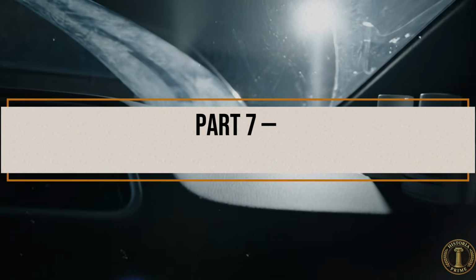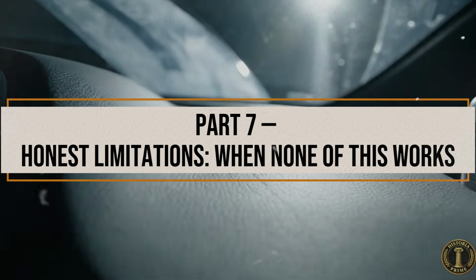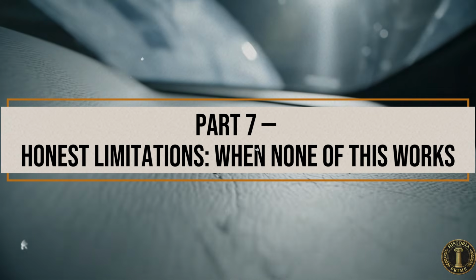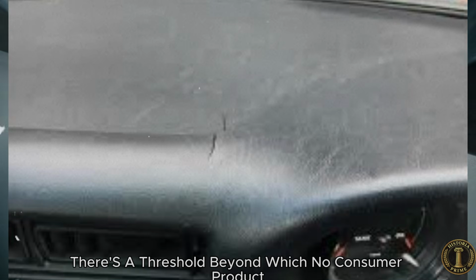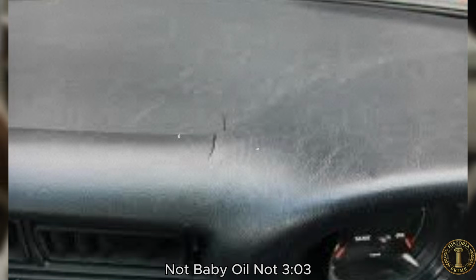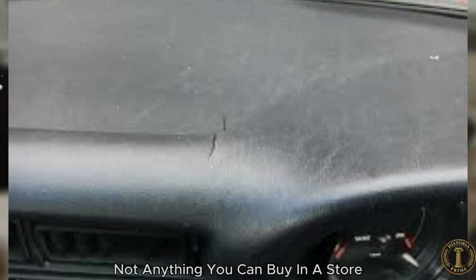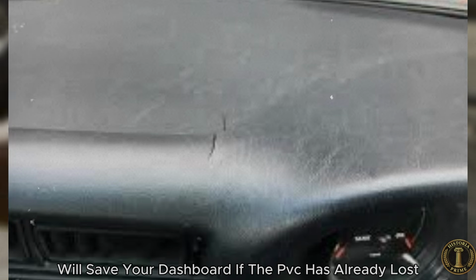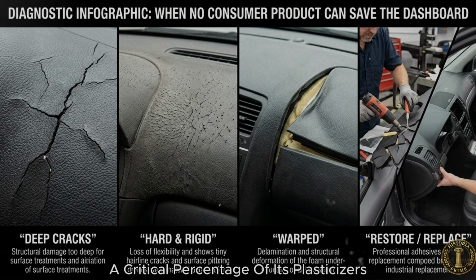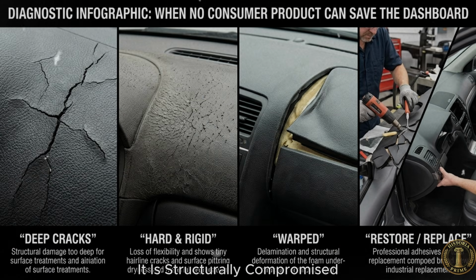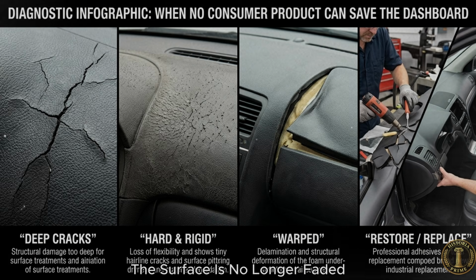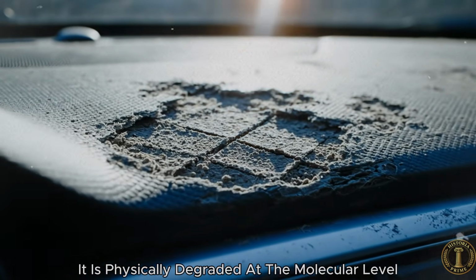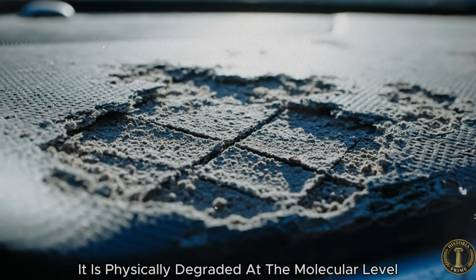Part 7. Honest limitations when none of this works. There's a threshold beyond which no consumer product, not baby oil, not 303, not anything you can buy in a store, will save your dashboard. If the PVC has already lost a critical percentage of its plasticizers, it is structurally compromised. The surface is no longer faded. It is physically degraded at the molecular level.